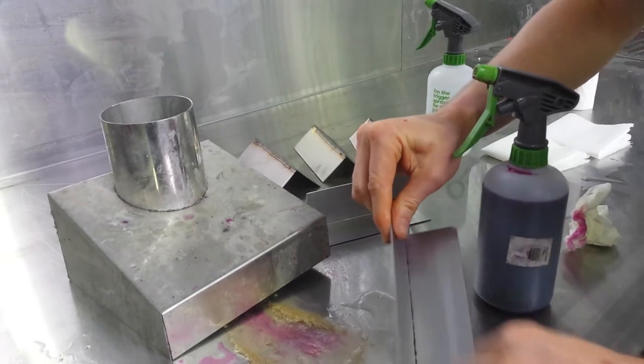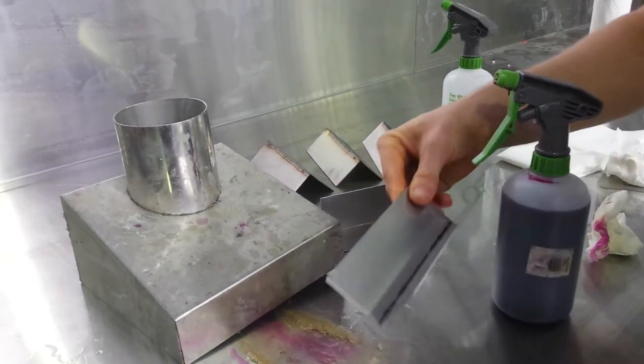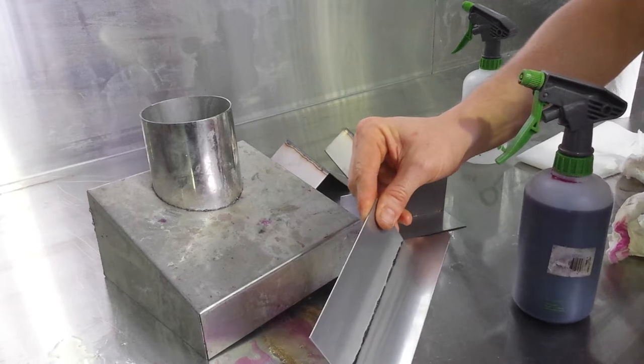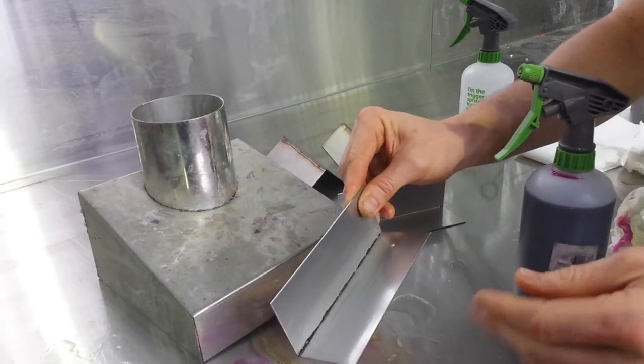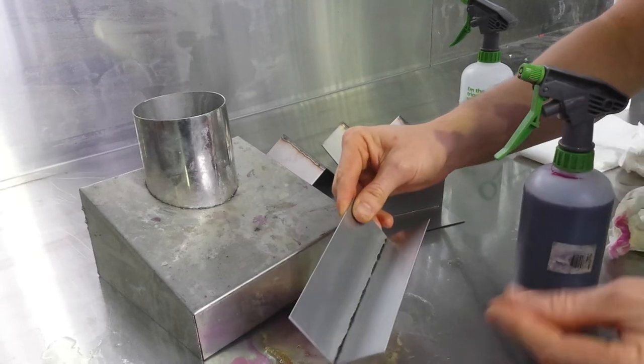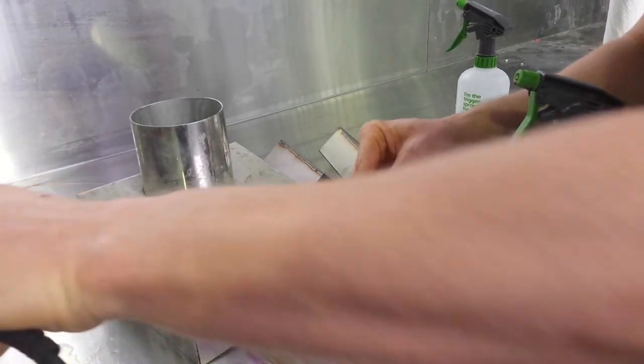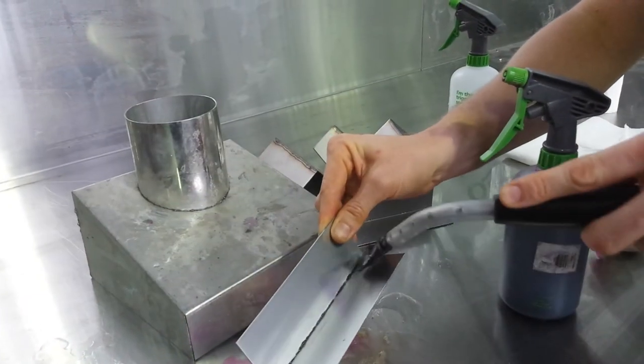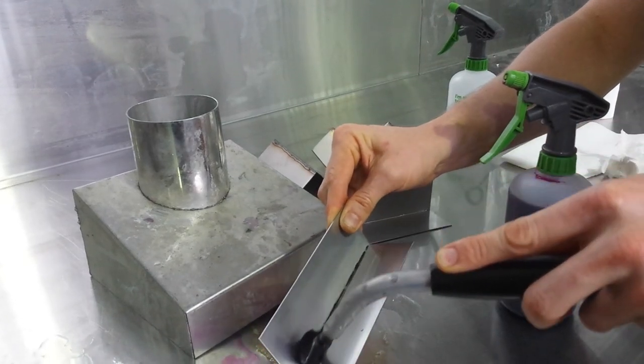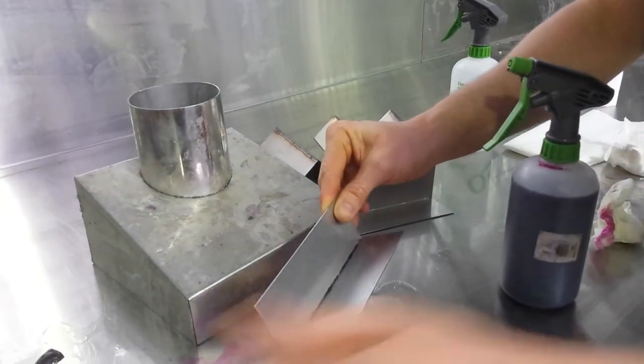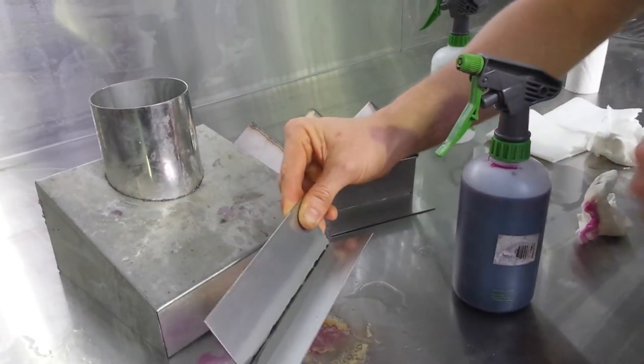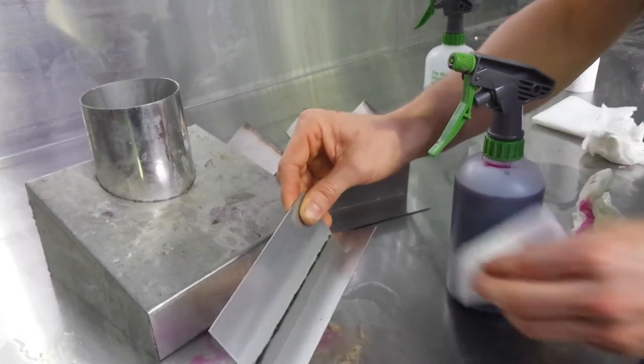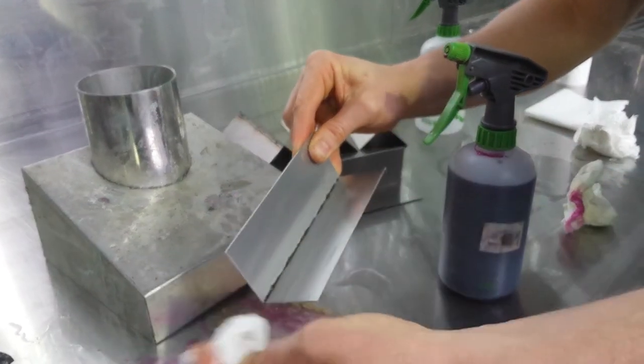Okay. So this is the ideal system in removing the weld cleaning solution and the neutralizer and leaving a dry workpiece that's not going to stain. So we will just, again, clean it with the weld cleaning solution. Now, that neutralizer fizzed quite a lot then because there's still a lot of solution left. The best method is to remove the bulk of the weld cleaning solution first.